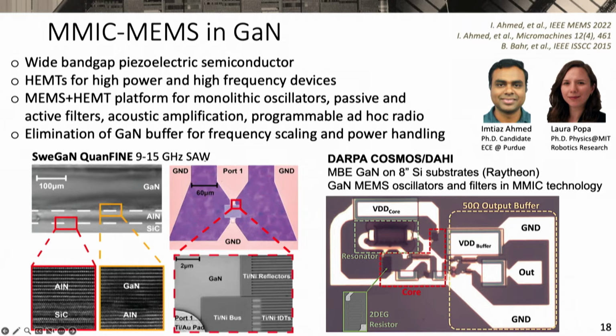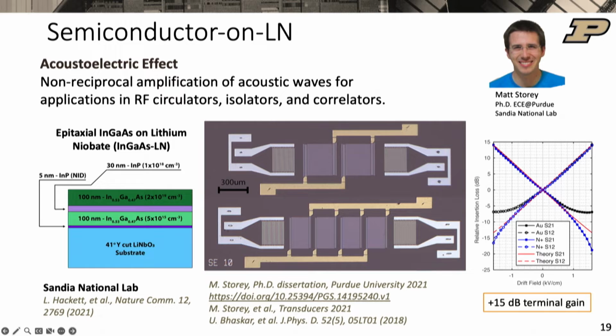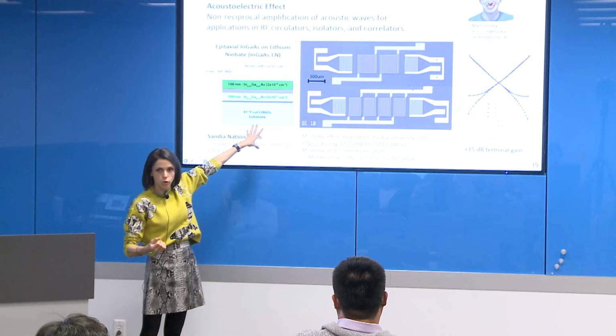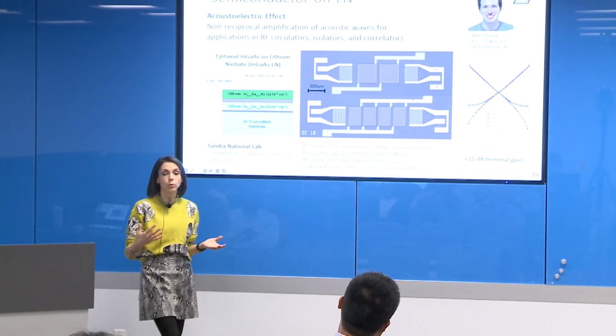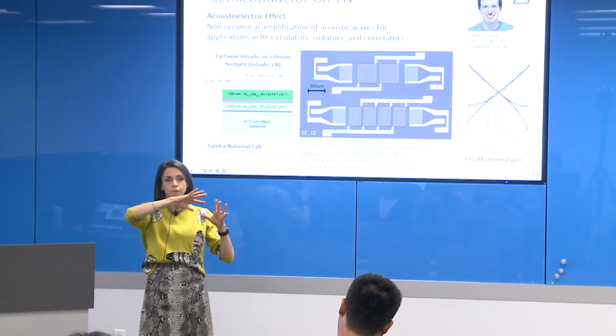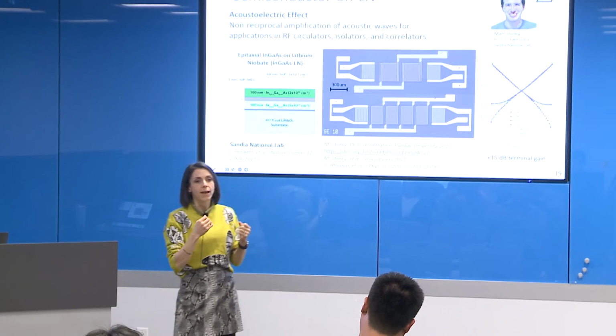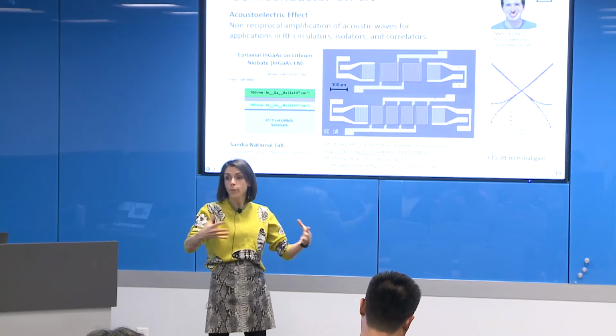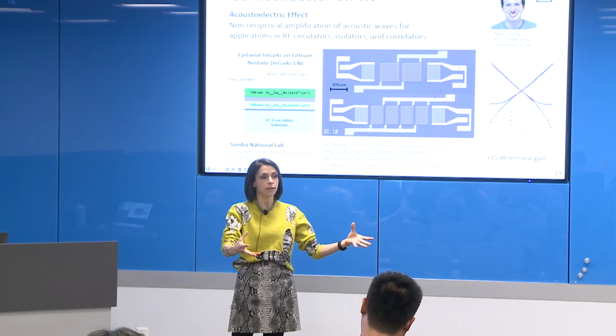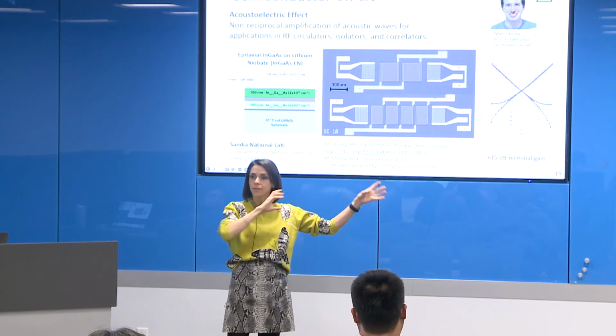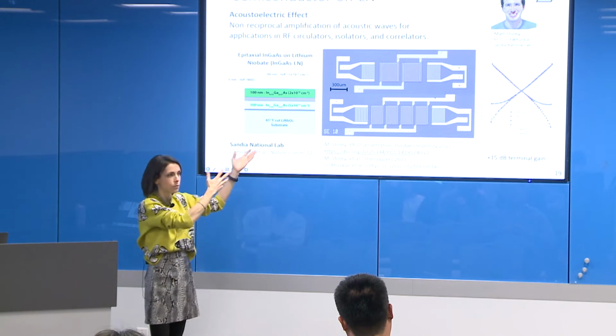Gallium nitride is one capability, but if we're going for the best material for the job, let's really dig in. Sandia National Labs developed a gallium arsenide on lithium niobate stack. And the beautiful part there is that the gallium arsenide has all the active devices that you'd want with high mobility and so forth. The lithium niobate, a strong piezoelectric, gives us access to surface acoustic waves. And with this, you can launch acoustic waves and have them interact with these active devices right at the surface. And when you have a piezoelectric wave, it generates a deformation potential, basically an electrostatic potential, right?